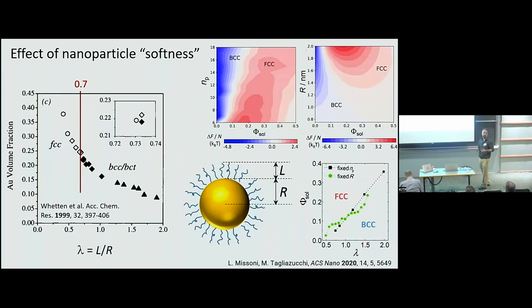And we can also look at this problem of the softness parameter and see if the theory also captures it. So as I mentioned before, for dry superlattices in this paper, you got the transition at lambda equal 0.7. Of course, the lambda required for the transition will not depend on the amount of solvent, because by changing the amount of solvent, lambda is fixed, but the transition shifts. So what I have to do is to plot the lambda for the transition as a function of the amount of solvent. This is the volume fraction of solvent in the whole lattice. And you can calculate lambda in two different ways. You can change the radius of the particle but keep fixed the length of the ligand, or you can change the length of the ligand and keep fixed the radius of the particle. Those are two ways of changing lambda. And both of them give more or less the same results.